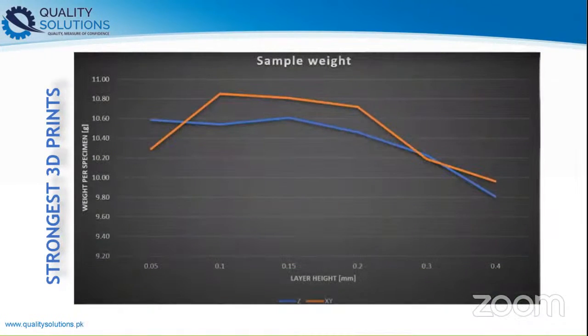As mentioned in the beginning, printing time is inversely proportional to the layer thickness, but the first interesting result was that not all the hooks weighed the same. As you can see on the screen, the higher the layer thickness, the less the part weighs, which is probably explainable by the fact that thicker layers have more gaps and are therefore less dense. We will keep these values in mind when we look at the strength later.